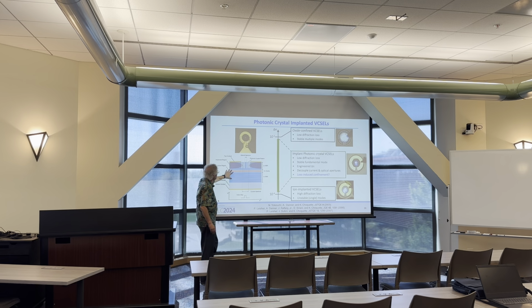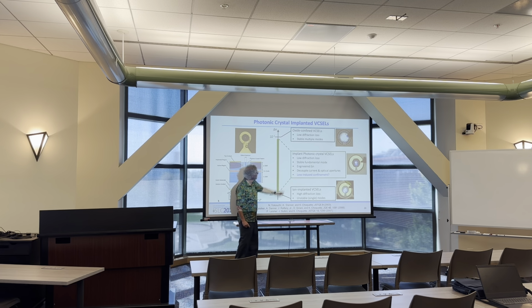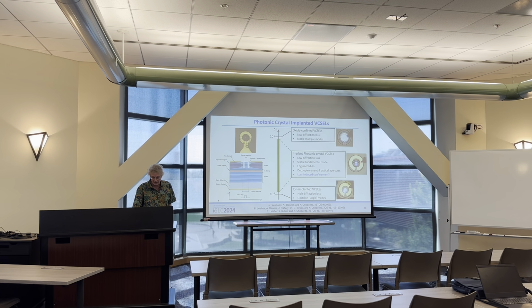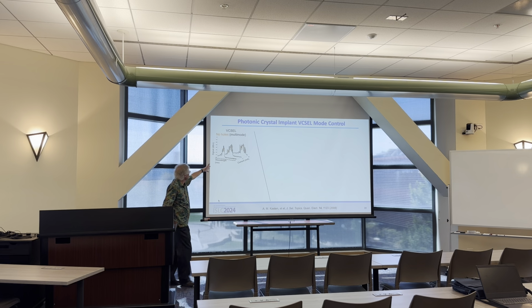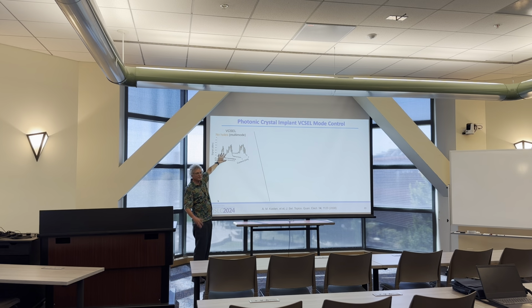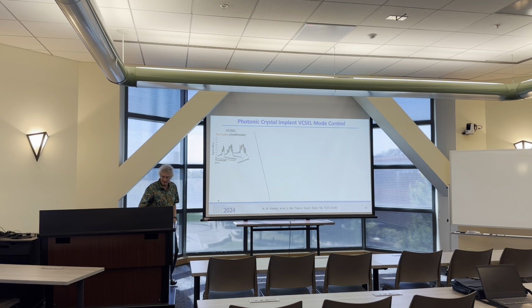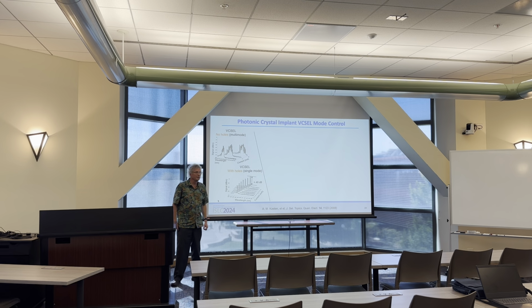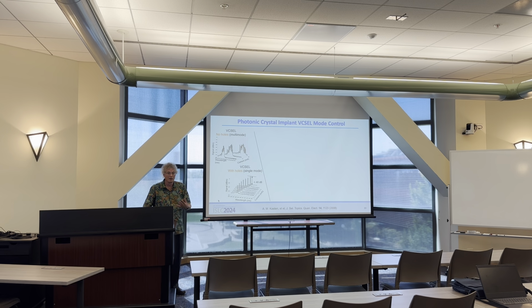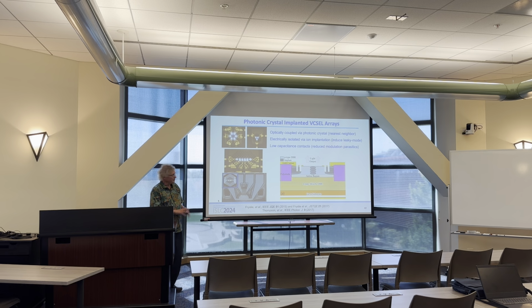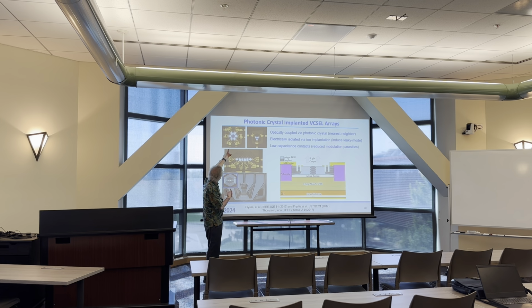But the implanted oxide-confined VCSEL allows us to actually design, and that's kind of what we've been doing over the years. So you can take this multi-mode, high-efficiency VCSEL, drill holes into it, and basically make it a single-mode device. And the other part that we like, because it makes it a lot easier, is you can use the same design at different wavelengths. There's a so-called easy single-mode configuration. And so this is my last slide. Now we look at these for making arrays. And what's interesting is in order to induce this coupling, we're trying to exploit this injection aspect.